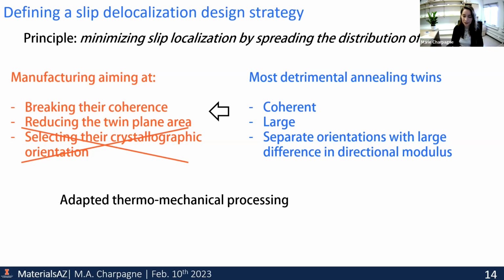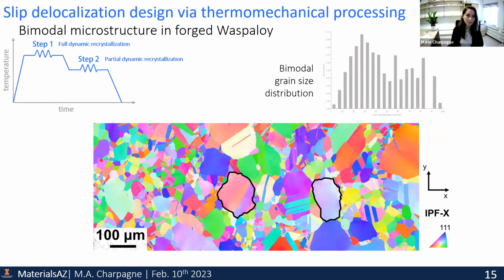And this was done by adapting the thermomechanical processing of our alloys. So this is the first example I want to detail now. We came up with a modified forging sequence for a different material, but it doesn't matter, another FCC superalloy called the Waspaloy, where we have an adapted process that consists of a first step where we forge our material at high temperature to trigger full recrystallization. As we are forging at high temperature, we call this dynamic recrystallization because recrystallization is happening dynamically as we deform the material. So we end up with a first category of very large grains that are dynamically recrystallized,